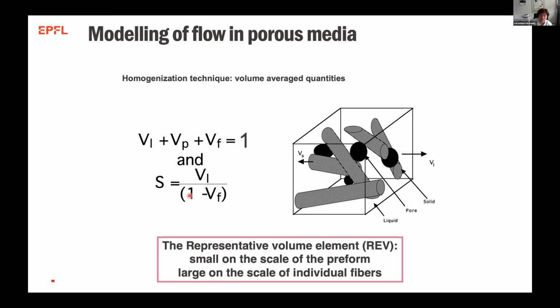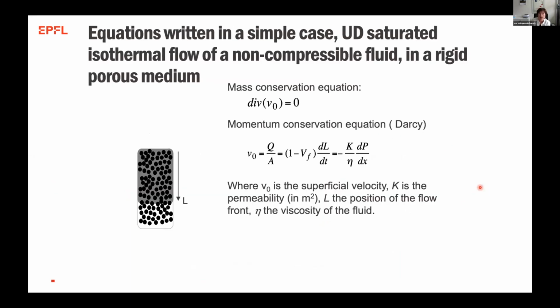So you need to model what's happening during flow, and you can do it using representative volume elements and typical fluid mechanics calculations. You have the volume fraction of liquid, pores, and fibers, and then you have the saturation, which is the volume fraction of liquid over the available space. Saturation is equal to 0 when the fabric is dry, and equal to 1 when the fabric is fully filled with liquid. I will run you through some equations, but I will make it simple. We assume a unidirectional, saturated, isothermal flow of a non-compressible fluid in a rigid porous medium. So everything is basically static except the fluid moving.